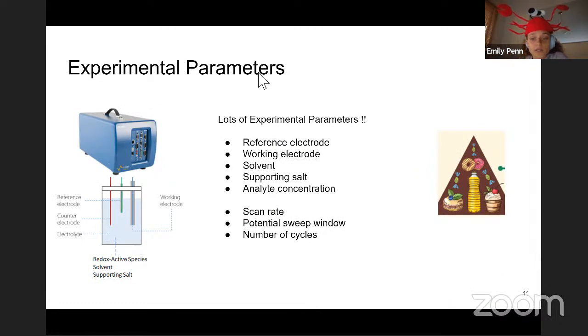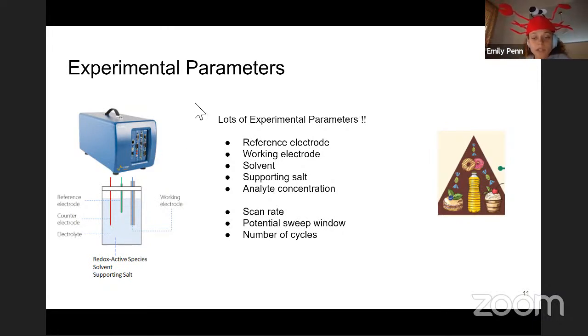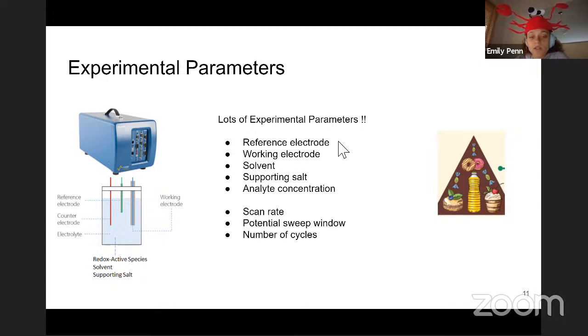The final part of the CV pyramid is the experimental parameters. There's a lot of different experimental parameters that you can control in cyclic voltammetry, but also in three-electrode cells in general. One really important one is the reference electrode. I mentioned previously that there are different reference electrodes that you would want to use for different systems. That's important because you want your reference to be at a constant potential so that you have a stable reference and it's not drifting during the experiment, because that would affect your results.